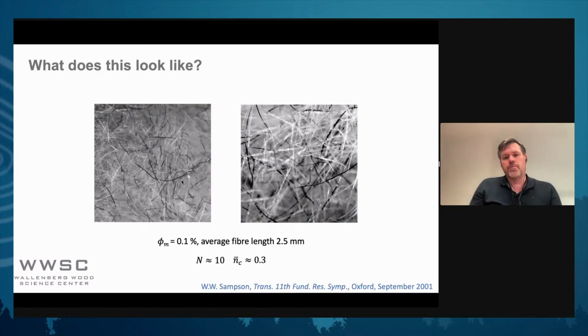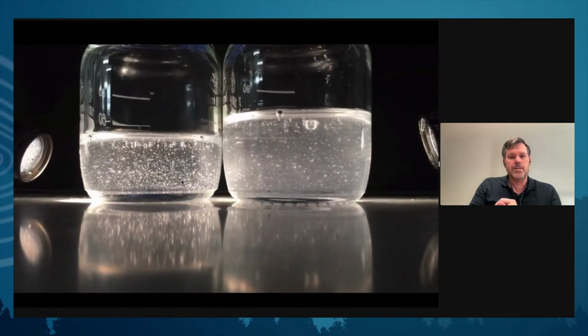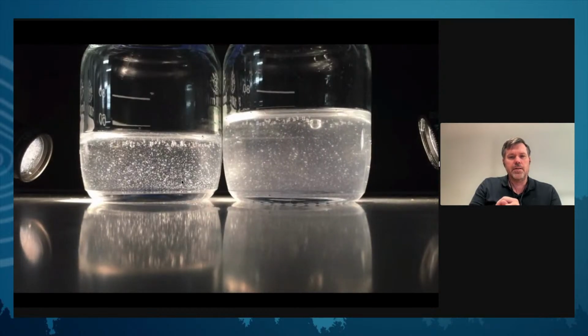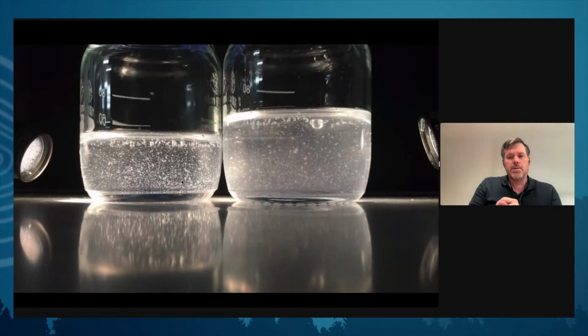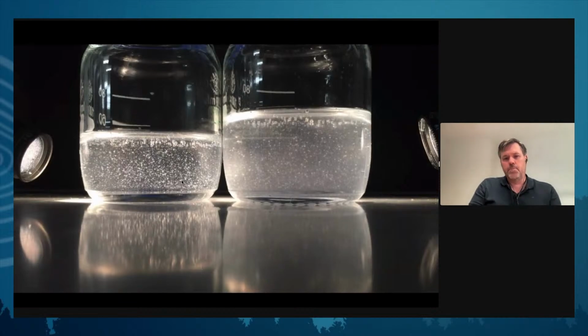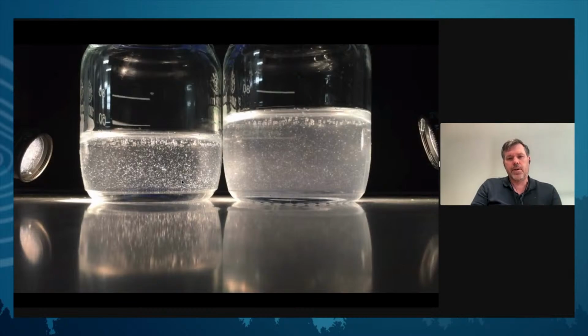And of course, if it was a very flexible polymer, you wouldn't get this behavior either. So just illustrating, to the left is 0.2%, and to the right is 0.3%. And we can see that big bubbles that have a strong buoyancy are rising, but the small bubbles stay. This is not a connected system theoretically if you assume stiff rods. You need a semi-flexible system of fibrils.